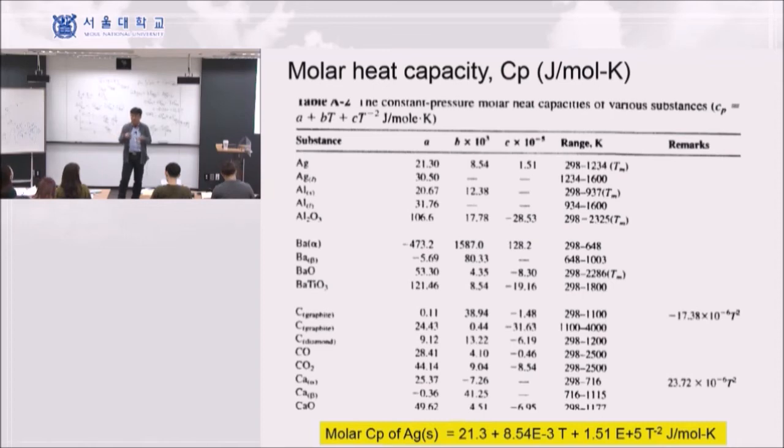Okay? Because it's not tight bonding, there's no restriction for the vibration anymore. So heat capacity is reasonably constant with temperature in the liquid state. It's the same for the gas phase. Theoretically it should have a certain temperature dependence term. It only shows you about 1600 degrees Kelvin; above this there's still liquid phase, but it's just measured in that limited temperature range. So that's all good.